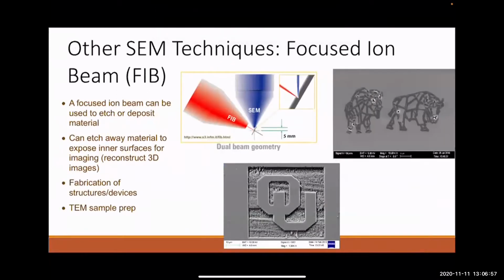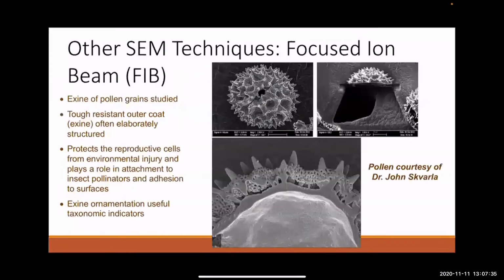Our Zeiss Neon has what's called a focused ion beam as well. So you have an SEM as well as a focused ion beam that's available. And what that means is ions are much more massive than electrons. And so when they hit the material, they'll actually damage it. And that can be a good thing because you can then use the focused ion beam again to create patterns like OU or this buffalo here, or to actually cut into material and look at the interior of it. And so combining the FIB to do the damage or the etching and then do the imaging with the SEM column, you can have a whole lot of cool applications.